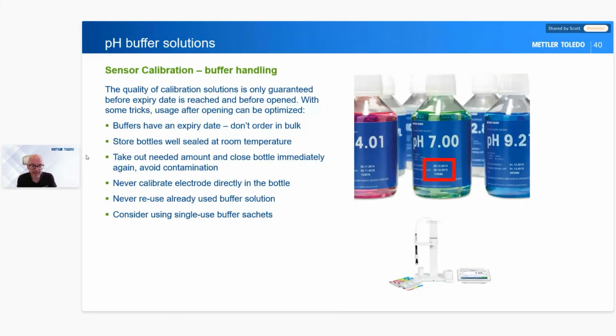We always take buffer solutions out into a smaller bottle and then measure into a small capsule or a small bottle, never directly into the solution. The other thing is we never keep that little bit. So once we take a pH measurement, a calibration and adjustment, once we've used that buffer, we throw it away, because that little piece can become contaminated. So we take the buffer measurement, we throw it away. The next time we do a buffer, we decant some fresh solution and use the fresh solution and then throw it away. So we're using it all the time. And that's really important to keep the measurements accurate, keep the calibration accurate.